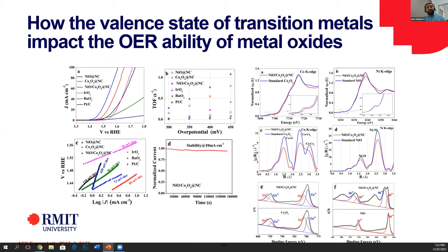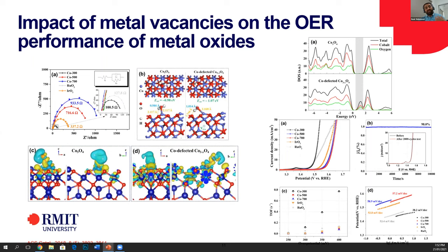We tried another way. The best thing that is required is the higher oxidation state. So rather than making something complex, can we find some way that we can still have a higher oxidation state in the simplest system? We found that we can create some metal vacancies. Non-metal vacancies are traditionally used, but metal vacancies are a less used method.